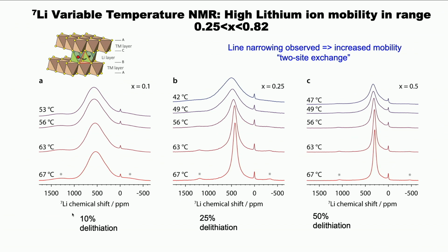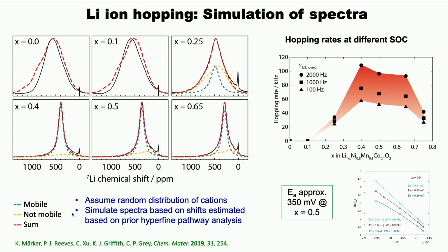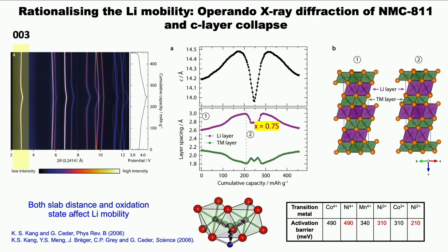And this, to a material science audience, is not that surprising. You have vacancies, and so you have room for the ions to move, and you actually needn't have that many vacancies for it really to go fast. And so what Katerina, my postdoc, did was to simulate these spectra and extract the hopping rates for transport. And so if you go from about 20% removal to about 70% removal, you have hopping rates of about 80 to 100 kilohertz. So these ions are moving very fast in these structures.